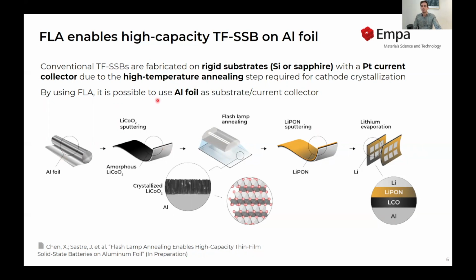So this is how the processing looks. We took aluminum foils and coated them with amorphous lithium cobalt oxide by sputtering. So no interlayers, no barriers, no additional current collector, directly onto the aluminum foil. We then use the flash annealing process for crystallizing the LCO into its layered oxide structure. Then we coated LiPON as a solid electrolyte, and we deposited lithium metal as the anode.